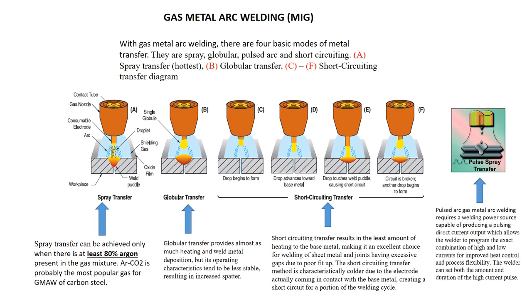Then you have the globular type transfer, which is almost as hot as spray, but its operating characteristics tend to be less stable, resulting in increased spatter. Your coldest type of transfer is short circuiting transfer, which results in the least amount of heat to the base metal, making it an excellent choice for welding sheet metal and joints having excessive gaps due to poor fit-up. The short circuiting transfer method is characteristically cold due to the electrode actually coming into contact with the base metal, creating a short circuit for a portion of the welding cycle.